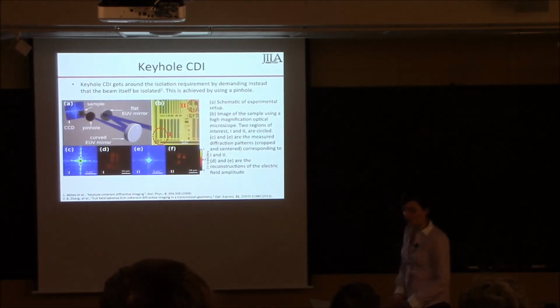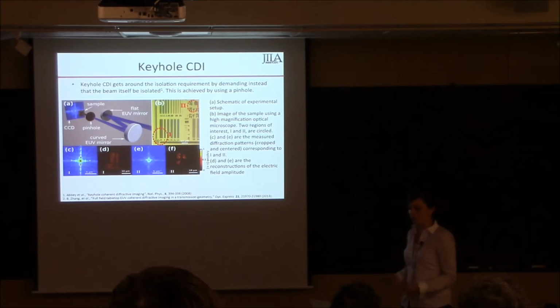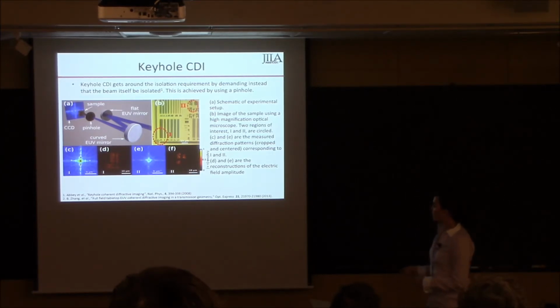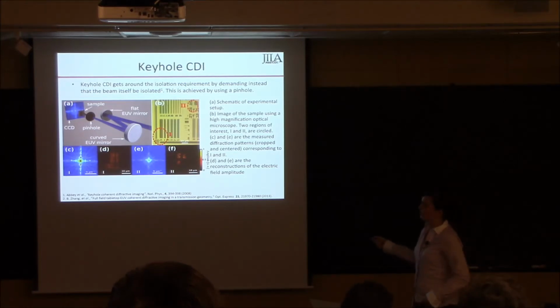In the past 5 years or so, a technique known as keyhole CDI has come out, and it allows an extended, non-isolated sample to be used by demanding that the beam be isolated rather than that the sample be isolated. And this can be achieved pretty simply by using a pinhole. So here's the schematic for that. It's similar to the previous one, just with the addition of the pinhole.